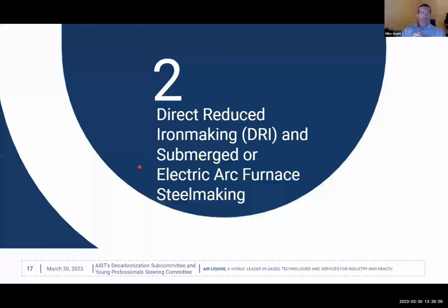But here in Europe, most of the major steel companies have now announced that they're going to switch to direct reduced iron, because of this limitation that hydrogen has with the blast furnace. 10% is not enough, and so the steel companies are being forced to plan for direct reduced iron making with either submerged arc furnace or electric arc furnace steel making.